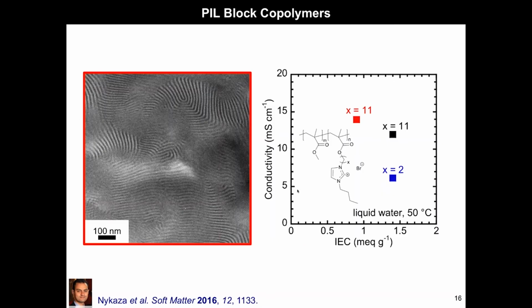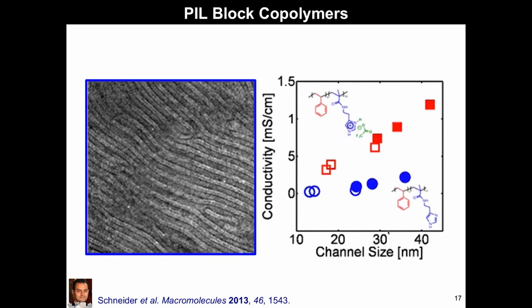Here's another example where you can see that we've increased the side chain on the polymerized ionic liquid block from 2 to 11, and you can also see this has an impact on the mobility of the ion group within that microdomain, and that also can increase conductivity at a similar ion exchange capacity. And here's some work from Rachel Segalman's group, and they also show something similar but much more quantitative. Here you can see a plot of the conductivity versus the channel size, and you can see as the channel size increases, or you increase that mobility in the microdomain, you can see an increase in the conductivity.